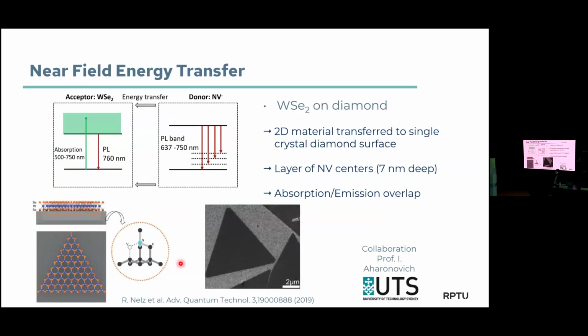So you mentioned that you use these layers of NV centers 7 nanometer deep. So first of all, how do you determine this depth? This is calculated from the implantation energy of 6 kilo electron volts, right? So it's 7 nanometer plus minus. Yeah, of course, I know, that's why I was asking. And second, have you tried to go even shallower with the NV, or did you find this is the optimum for the FRET measurements? I must admit, we did not try shallower yet. It was for a technical reason, because for the implanter, this was the minimum energy we had. So we went to the 6 kV. I see. Thank you.